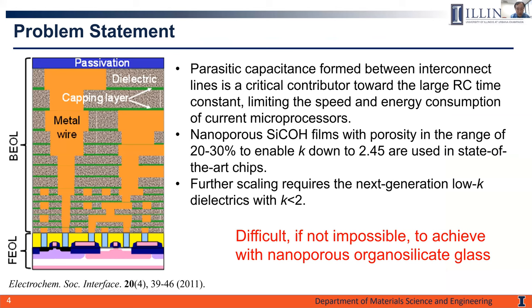And we know since the 90 nanometer technology nodes, the low-k dielectrics, which is in the form of nanoporous organosilicate glass, has been introduced by the industry to replace silicon dioxide as the interlayer dielectric to mitigate this problem. Currently, such nanoporous silicon dioxide film, we dope it with also carbon and hydrogen, they have a porosity in the range from about 20 to 30%. And they're gonna be able to achieve an effective dielectric constant down to about 2.45 in state-of-the-art chips.